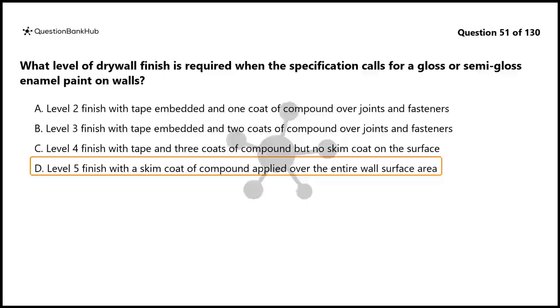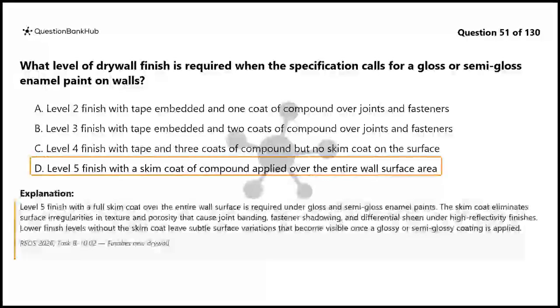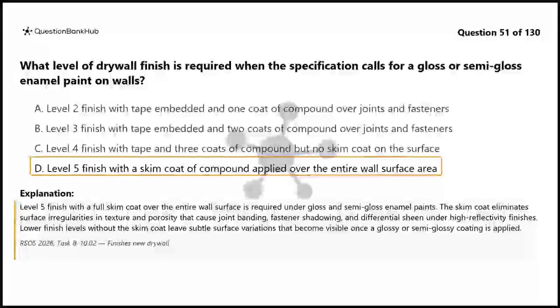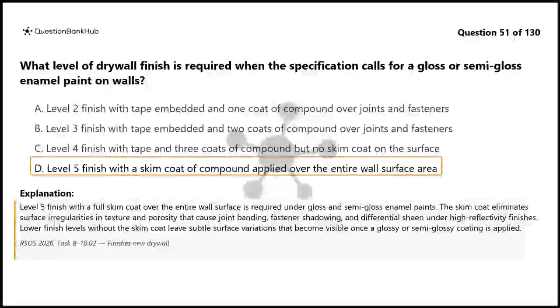The correct answer is D. Level 5 finish with a full skim coat over the entire wall surface is required under gloss and semi-gloss enamel paints. The skim coat eliminates surface irregularities in texture and porosity that cause joint banding, fastener shadowing, and differential sheen under high reflectivity finishes. Lower finish levels without the skim coat leave subtle surface variations that become visible once a glossy or semi-glossy coating is applied.